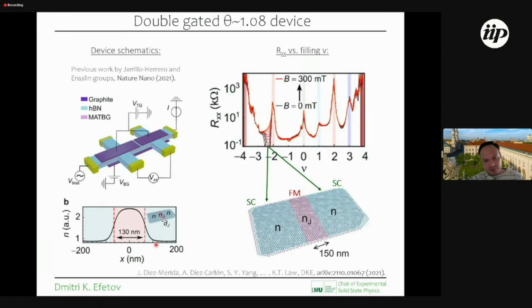So what effectively this geometry allows us to do is to create junctions where the leads of the device are tuned into the superconducting state and are kept superconducting, but the center region of the device is tuned into any other state in this phase diagram. It can also be tuned, for example, into this filling factor 1 state, which is magnetic. So in principle, this geometry allows us, by electrostatic tuning, to create homojunctions, again without any chemical doping, but really just by electrostatic gating, between superconducting phases and the magnetic phases, but also any other phases that we observe in the system.